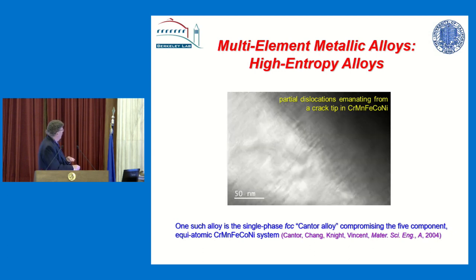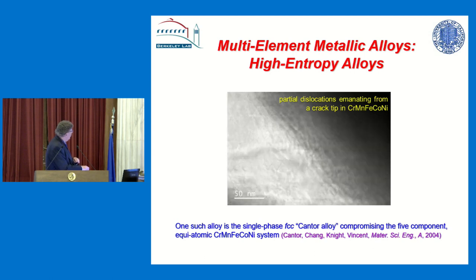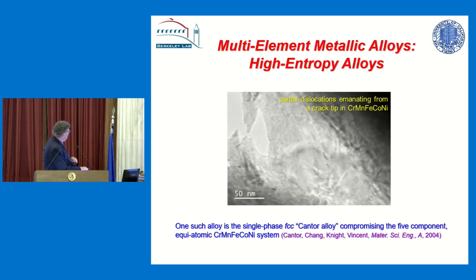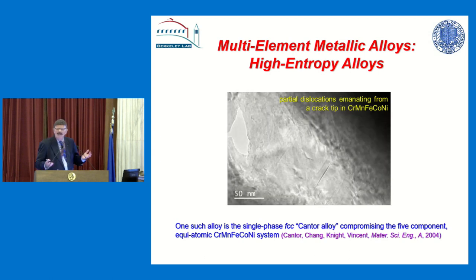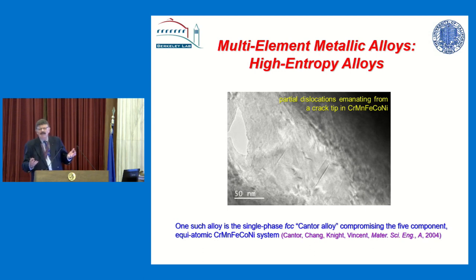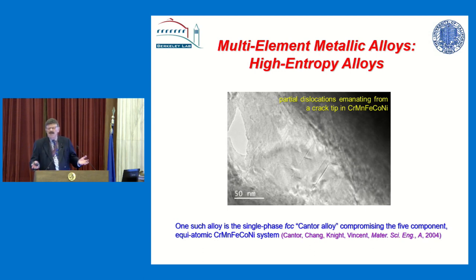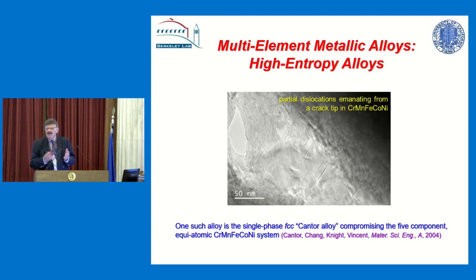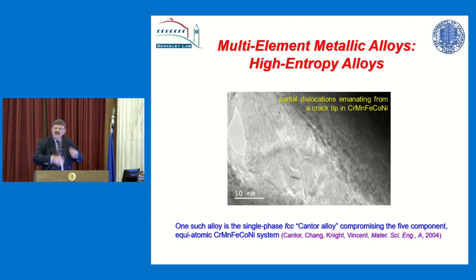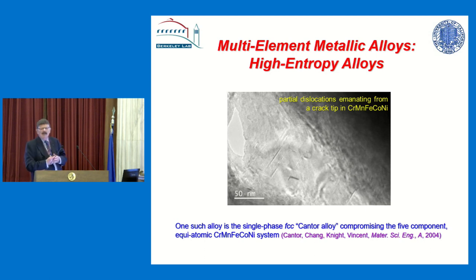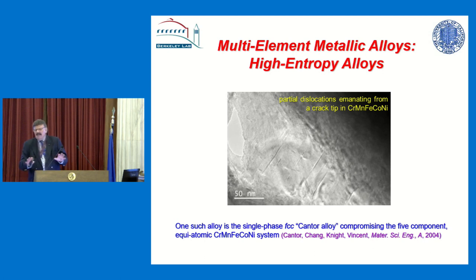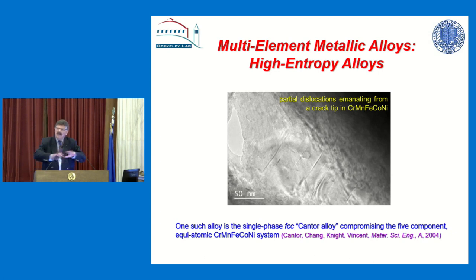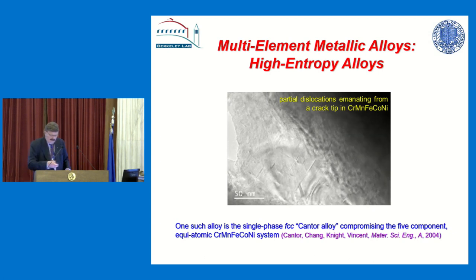And so one of the alloys of interest was this chromium, manganese, iron, cobalt, nickel. Five different elements, all with different crystal structures, but they form a single phase material, which is face-centered cubic, which is very, very interesting. You'd expect to see nasty intermetallics. And so this set up a whole new range of studies on these multiple element materials. The name high entropy alloy has stuck. There's nothing particularly important about the entropy, but it's their multiple principal element materials.